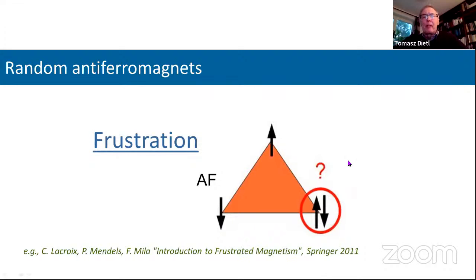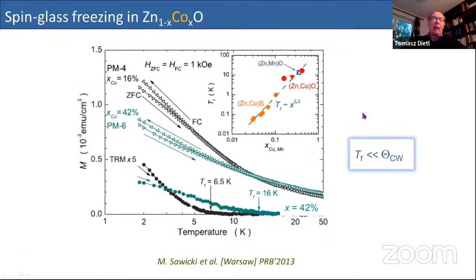What do we observe? It is known that random antiferromagnets have spin glass freezing at low temperature. And this freezing temperature depends on concentration, but for instance, it is 16 K for 42% of cobalt. So it's relatively low temperatures. This freezing temperature is much lower than the Curie-Weiss temperature because of the frustration present in the system.